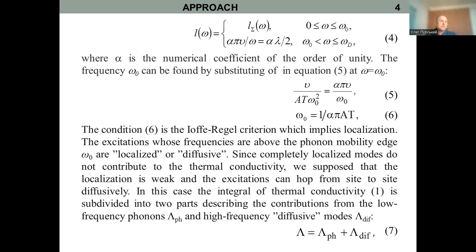Equation 6 is the well-known Ioffe-Regel criterion, which implies localization. The excitations above the phonon mobility edge are localized or diffusive. Since completely localized modes do not contribute to thermal conductivity, it is supposed that the localization is weak and the excitation can hop from site to site diffusively. In this case, the integral of thermal conductivity 1 is subdivided into two parts, describing the contribution from low-frequency phonons and high-frequency diffusive modes.